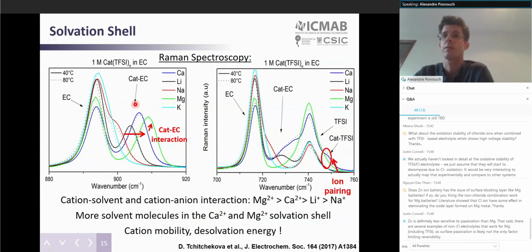And the strength of the interactions between the cation and the solvent. Here you can see the Raman spectra for TFSI-based salt using lithium, sodium, magnesium, calcium, and potassium. As we deconvolute these spectra, we can see that the cation-solvent and cation-anion interactions follow the polarizing power of the cation—strongest for magnesium, then for calcium, and so on.